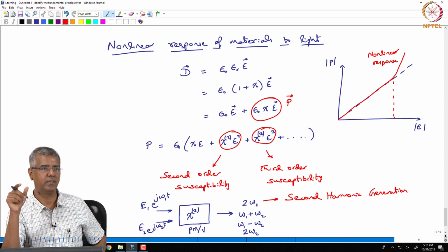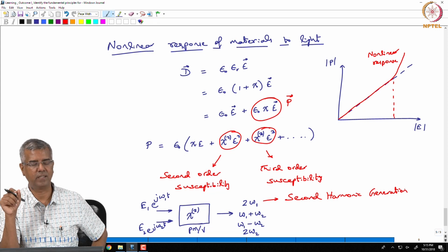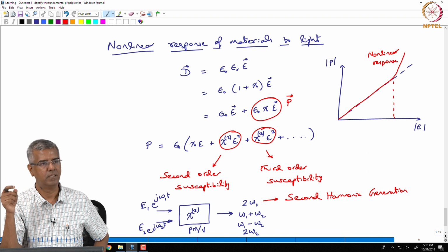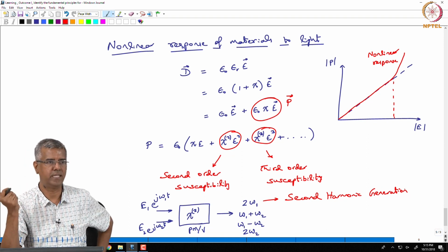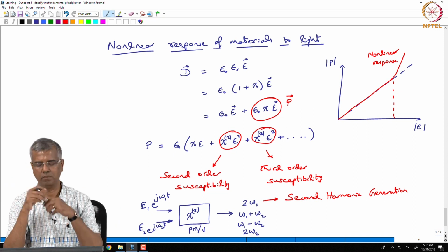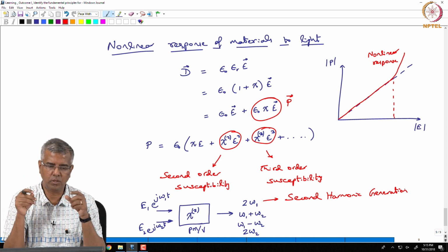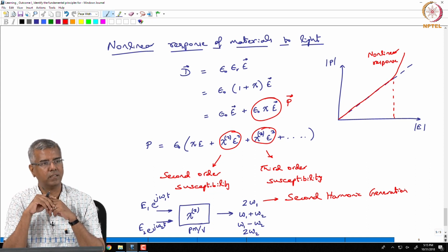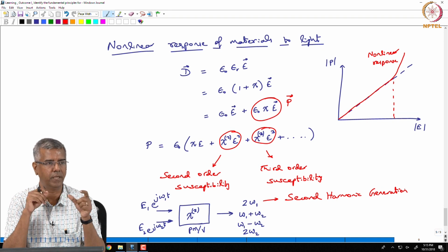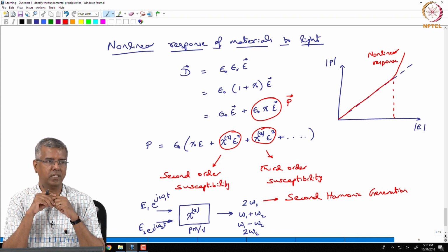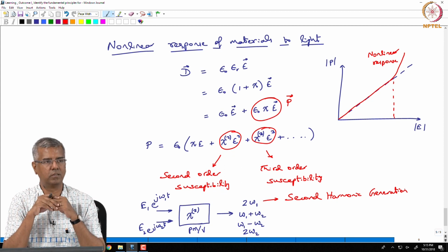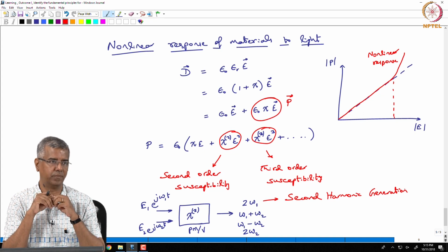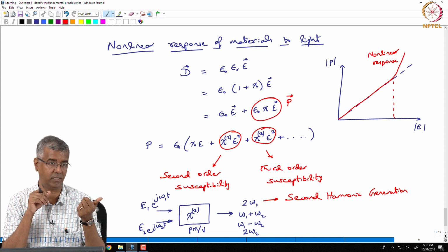So, you could make a 1064 nanometer laser out of a neodymium crystal if you can pump it with some radiation around 810 nanometers, okay. So, in that laser pointer you have an 810 nanometer laser that is actually pumping a neodymium YAG crystal which has got mirror coatings on either end. So, you can actually make a laser out of that. So, that laser is happening at 1064 nanometers,